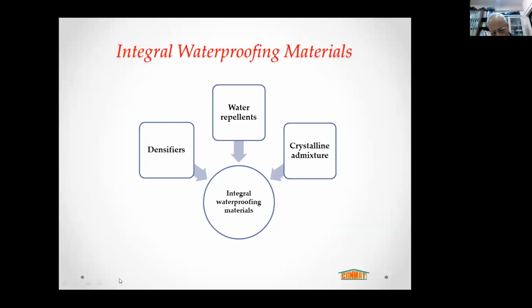But intrinsically, what I wanted to mention here is that these can be categorized as densifiers, water repellents, and crystalline admixtures. And we tend to even confuse these three different categories, and we qualify one with the other. The densifiers are basically the approach where you don't try to leave calcium hydroxide as calcium hydroxide in your concrete system. You convert it into a densified microstructure of different hydrate systems, which you do otherwise also, for example, with concrete, with supplementary cementitious materials.